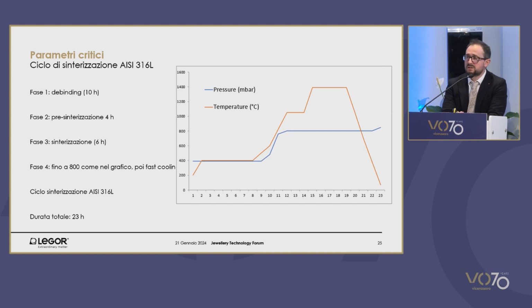This is the standard sintering cycle for stainless steel. We have phase 1, debinding, which has been extended significantly because of the shape of these items. This is similar to the cycle of microfusion with chalk. In the case of investment casting, we got wax. Here we got the binder, so it's a different thing. And then we have the curve that represents a sintering phase.